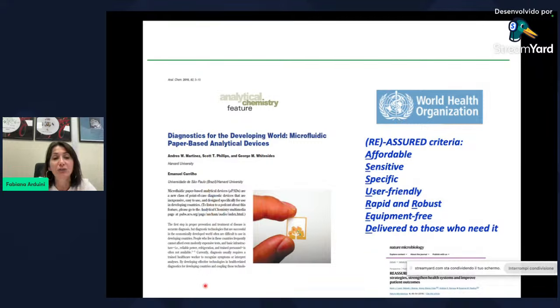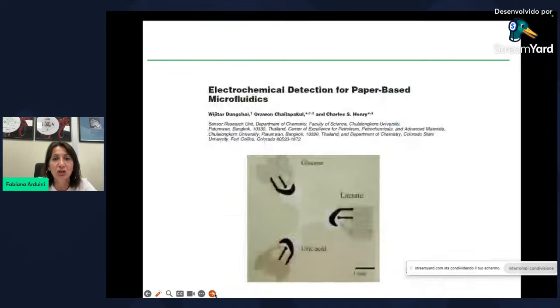So the first article that used this approach, but with electrochemical detection, was reported in the Analytical Chemistry journal by Professor Henry Group, in which they produced a three-electrode system printed on filter paper and modified with Prussian blue as electrochemical mediator, with glucose oxidase to detect glucose, lactate oxidase to detect lactate, and uricase to detect uric acid. But of course, if we put a drop of water on filter paper, there is diffusion of the solution, thanks to the capillarity-driven properties of the paper.